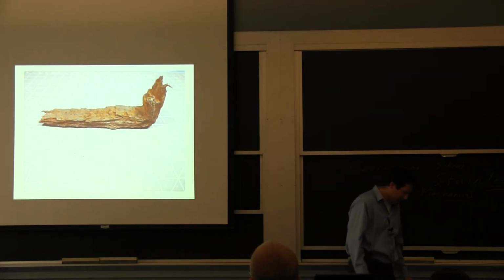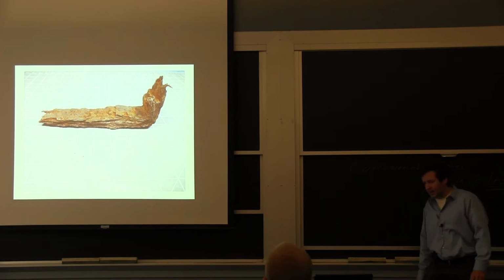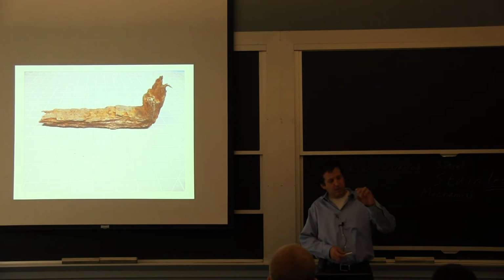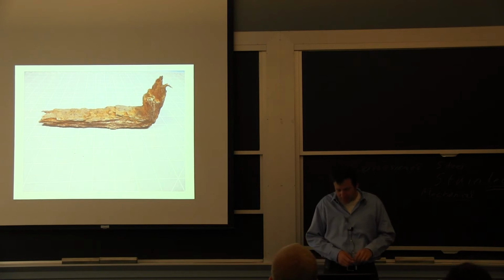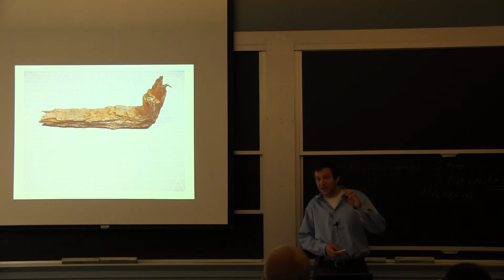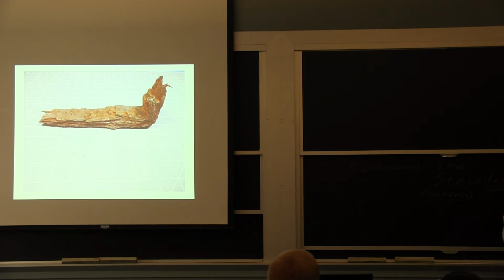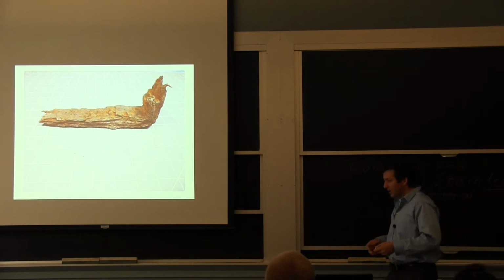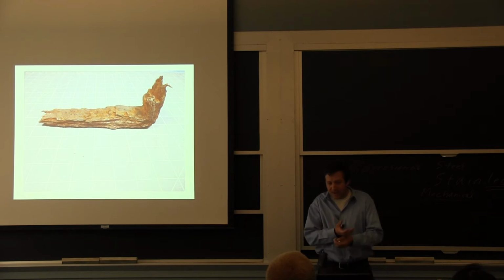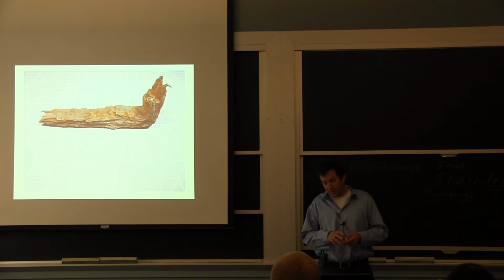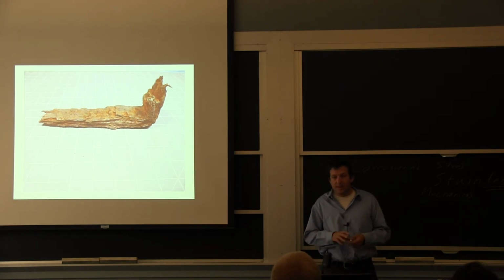So we're talking about steel, and this is a piece that came out of the Storrow Drive tunnel. I was looking for it, but I couldn't find it this morning. It's about 3/4 inch thick, but it is not the thickness of the material you lost, thankfully, because this came out of a 1 inch beam. What happens with corrosion of steel is it just exfoliates, it just grows. The oxide has a much lower density, and it's not a compact and perfect crystal. It's just got a lot of oxide and loose pieces in it. So you grow by a factor of 4 to 5.